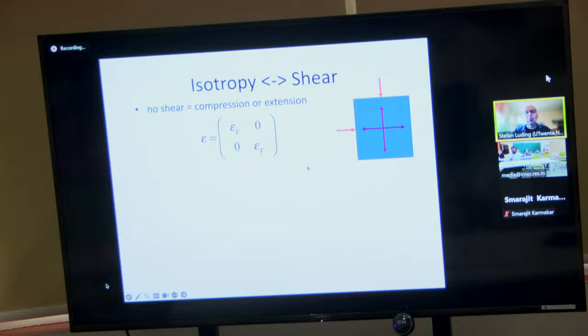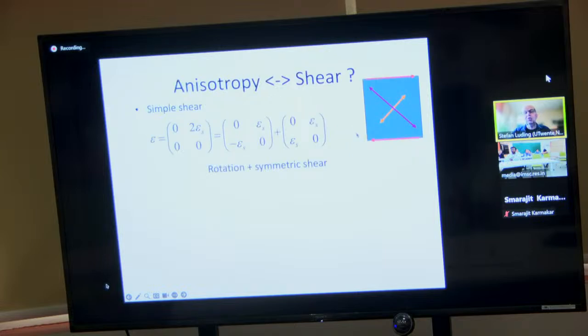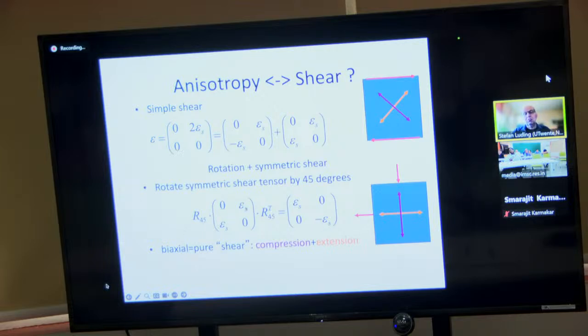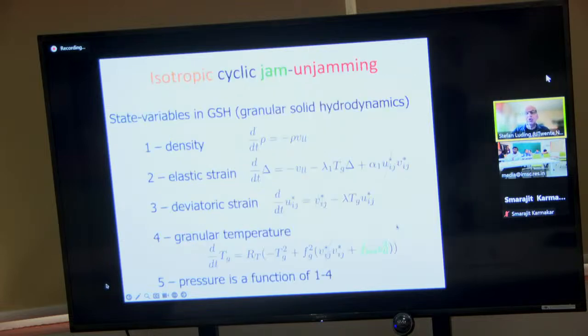And if I go, short excursion, isotropic versus shear, I just want to highlight again, we can have a two-dimensional simplified strain tensor, isotropic, only diagonal elements. Isotropic means you are compressing from both sides, for example, in the same way. Or we can have shear, and that can be simple shear, like upper side goes to the right, lower side goes to the left, and that means compression and tension in these two directions. Or we can have pure shear, rotating this by 45 degrees, which means compression and extension in orthogonal directions also. So we have isotropic and shear, just to make sure.